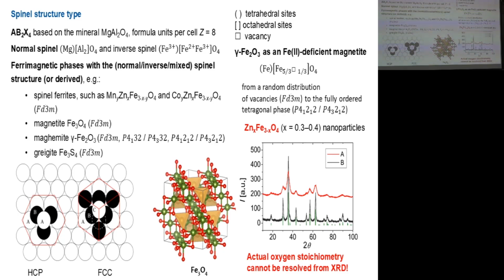And there are actually two ways how to arrange these hard spheres. But in this case, the oxide anions are arranged in a sequence of three layers, ABC, which are not precisely aligned, they are slightly shifted. So there is this sequence ABC, and if you describe it geometrically, and see it from the viewpoint of crystallography, you will see that it forms such face-centered cubic cells. So this is the arrangement of oxide anions, and you can clearly see in such arrangement that there are some holes between the oxide anions, and there are two kinds of holes: the tetrahedral holes and octahedral holes or sites. And these sites are occupied by the cations.